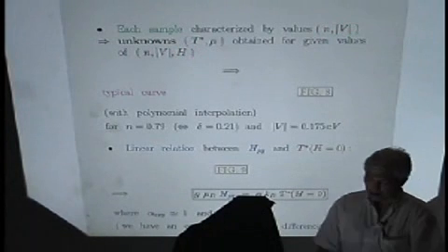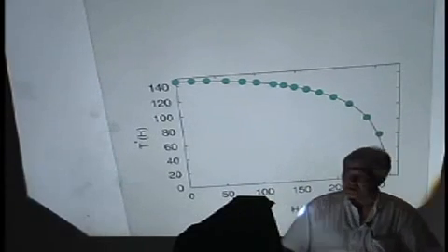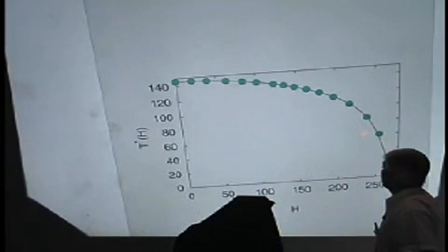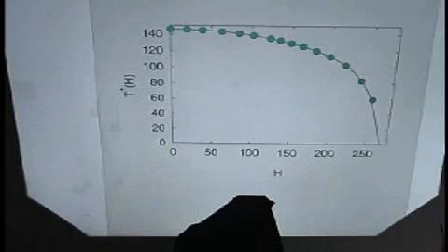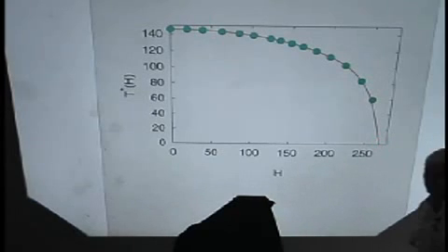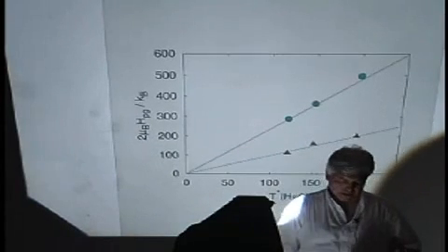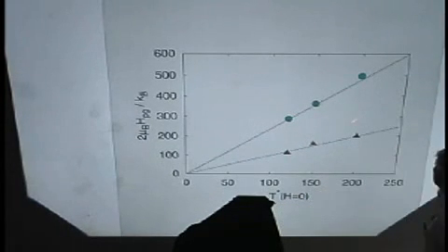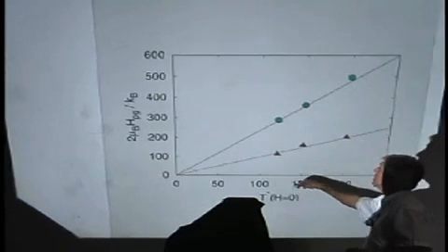A typical curve that you obtain is the following. So these are the theoretical values, and that is a polynomial interpolation to the values. And from this we extrapolate and we can identify this critical field here. We do it for several samples, and the curve that you obtain is the following. Again, these are the experimental values, with a line which of course has to cross zero here. These are the theoretical values.